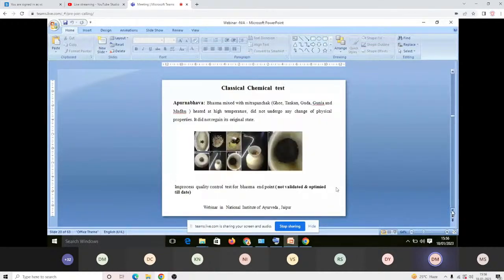I can cover the classical and chemical tests and the physical tests, such as the Apurna Bhava test and Mitra Panchak, where you add it and it does not return to its original state. In-process quality tests for the bhasma endpoint are nowadays not validated or optimized, but they are a good parameter if you apply design of experiment, QbD. According to Jadavji Tikamji, when you prepare bhasma of silver and gold, the heating pattern is low to high, and for abrak and iron bhasma the heating pattern is high to low. In that way every bhasma is unique.